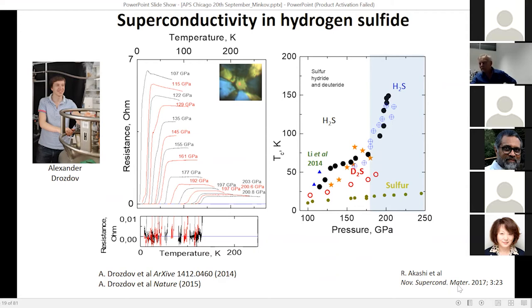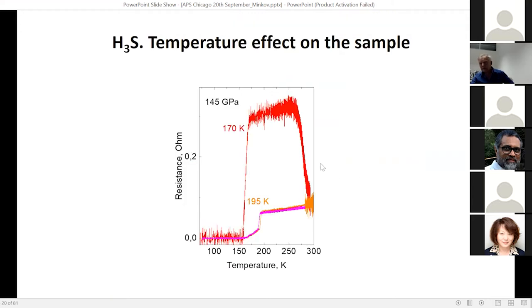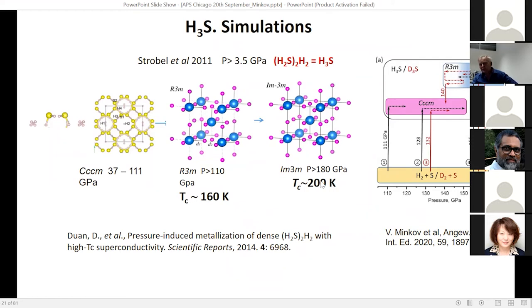Most interesting is what happened next: the critical temperature rocketed to higher values and we could not understand what was happening — this is still not very well understood. Akashi recently proposed it's a series of incremental transitions which increase the critical temperature. At the time we had no idea. One day we pressurized the sample at low temperature to high pressure and when we warmed to room temperature, the resistance dropped and we saw clear steps at high temperatures.